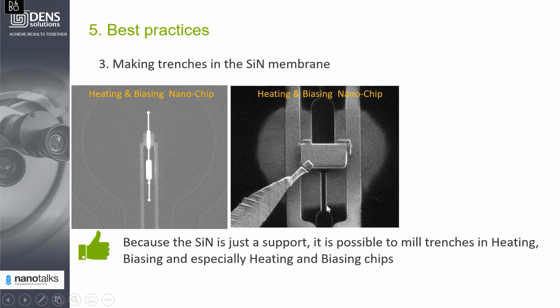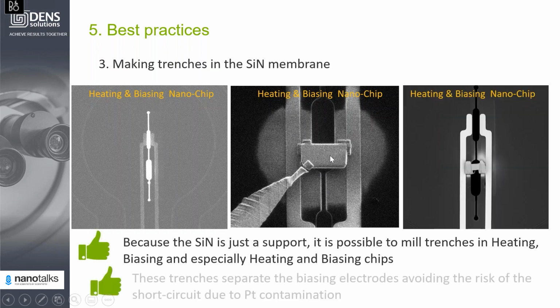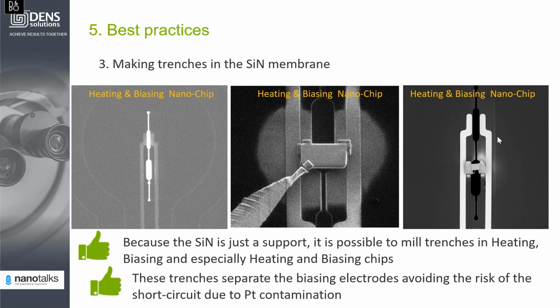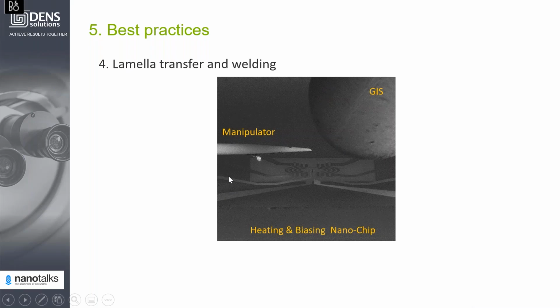And having those trenches will allow us to actually disconnect both electrodes. In this case, if you apply a voltage bias, the current will go through your sample, but not via the platinum contamination. So this is another example of a sample, and then you see the cuts here.